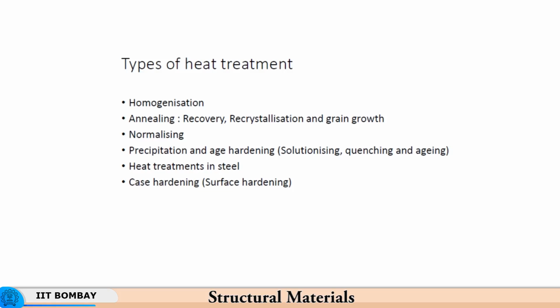Now, the advantage here is that if you have a large dislocation density, or if you have worked the material a priori, then the sites at which these precipitates will form will be much larger. Since the alloying elements are the same, the quantity is the same, but now it has to be dispersed over a larger number of locations, so you have very fine precipitates being precipitated at a given location. So, if you have worked the material, if the dislocation density is higher, defect density is higher, dislocation clusters form, then the precipitates would be finer and they will precipitate at a larger number of locations.